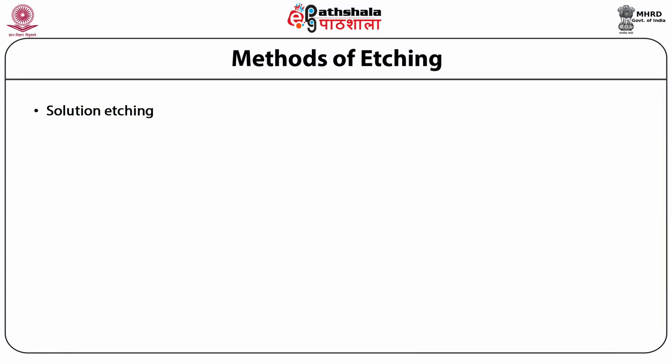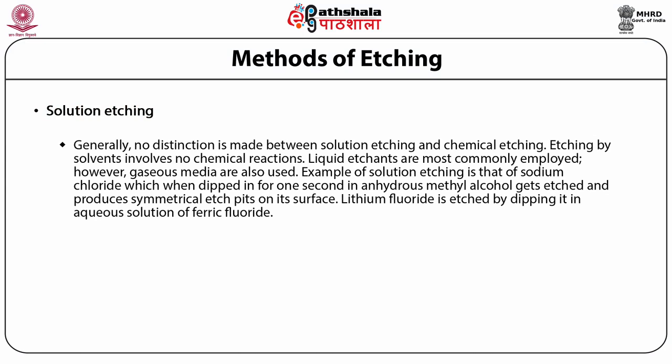Solution etching: generally, no distinction is made between solution etching and chemical etching. Etching by solvents involves no chemical reactions. Liquid etchants are most commonly employed; however, gaseous media are also used. An example of solution etching is that of sodium chloride, which when dipped for one second in anhydrous methyl alcohol gets etched and produces symmetrical etch pits on its surface. Lithium fluoride is etched by dipping it in aqueous solution of ferric fluoride.